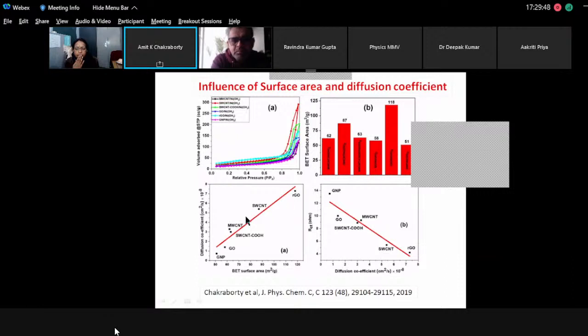And the bottom two curves were actually suggested by the reviewers. When we presented this, the reviewer suggested that we try to find a plot, because this is missing in the literature at the moment, of the relationship of surface area with the diffusion coefficient, because the diffusion coefficient is a direct function of the EIS, the charge transfer resistance from the Randles circuit. So we related them, and we find yes, for RGO, since it has the highest surface area, it has the highest diffusion coefficient, so the charge transfer happens very fast. And when you combine this effect with the RCT, the charge transfer resistance, we see a similar effect. Here, RGO has the lowest value of charge transfer resistance. Okay, so this is a major finding in our opinion.